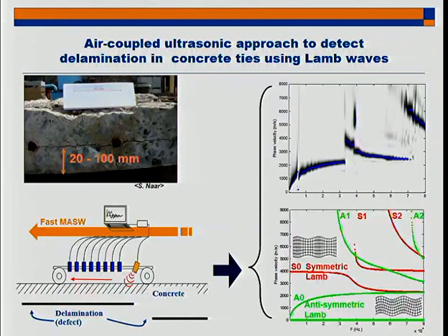But if you remember this delamination of the rail tie near the pre-stressing strand. So they corrode, they push out, and they cause this horizontal crack, a large planar horizontal crack that runs parallel to the top of the tie. So it's as if suddenly you went from a thick element to a thin element. If you imagine that this crack is so complete that now we had a thick element and now it's a thin element because of that crack. It's a plate now. Think of it as a plate. So we now have a situation where there are places where the concrete acts as a thin plate because we have a thin delamination through that.